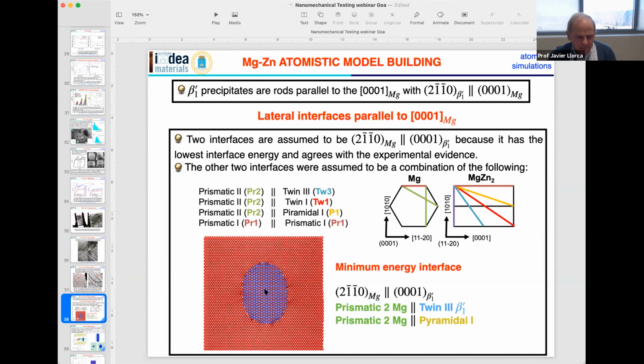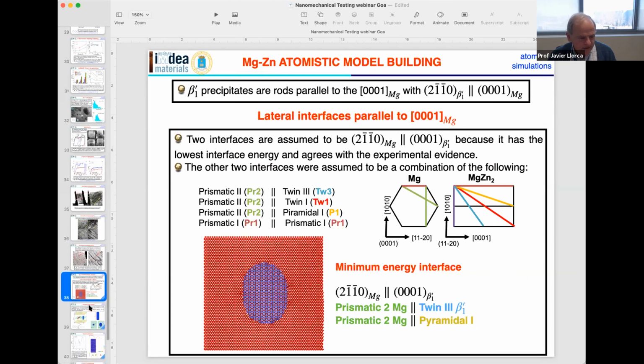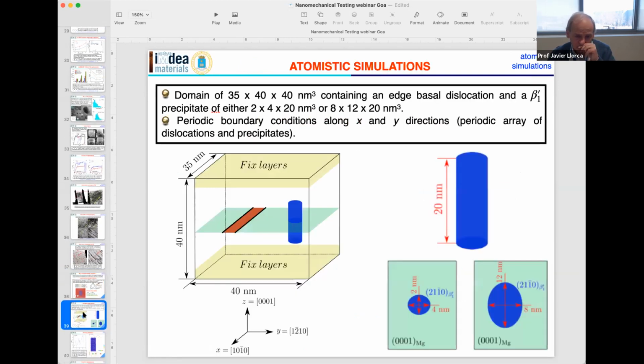We took a lot of care to build up the interface between the precipitate and the matrix, taking into account that these are minimum energy interfaces. This is something that is important. And then this is the model for the atomistic simulations. So you have a domain of 35 by 40 by 40 cubic nanometers. In this domain, this is the basal plane. In this basal plane, you have a basal dislocation that is dissociated, and perpendicular to the basal plane, you have the precipitate.